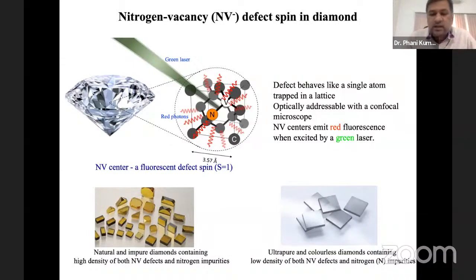This NV center can exist in more than one charge state, and what we refer to as the NV center is the negatively charged NV center, where a neutral NV center accepts a charge from a nearby donor. This NV minus has a spin of 1 because there are 2 unpaired electrons. So this defect behaves like a single atom trapped in a diamond lattice. There are two crucial properties of this NV center which make it very relevant for applications and also fundamental research.